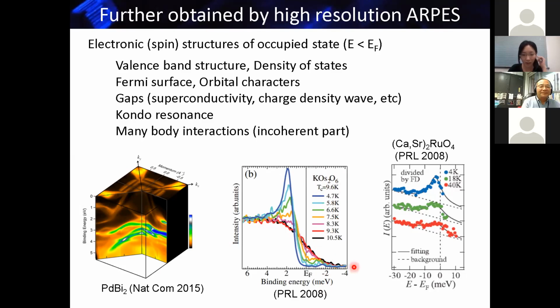At high temperature, it shows the usual Fermi-Dirac-like distribution at the Fermi level because it's a metal. But when you cool it down below the transition temperature, this nice superconducting peak appears, and we can estimate the gap from this spectrum like this. And also, for example, in strongly correlated systems, in some cases like a Kondo system, we can observe Kondo resonance type peaks appearing near the Fermi level like this. So we can get much information by using photoelectron spectroscopy. Okay.